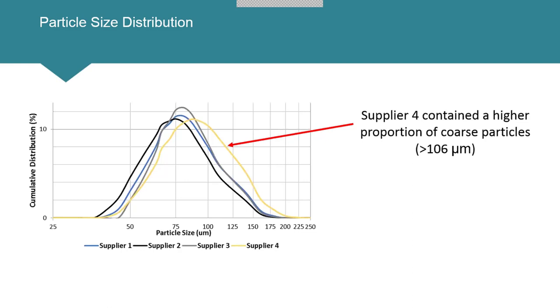What we can take from this chart is that supplier 4, for whatever instant reason, seems to have a higher proportion of coarse. That in itself is not necessarily an issue. Of course, we can post-treat this powder and take that coarse material out. We can sieve it, classify it in another way. But of course, that starts to affect yield. And what affects yield starts to affect then cost of the powder.